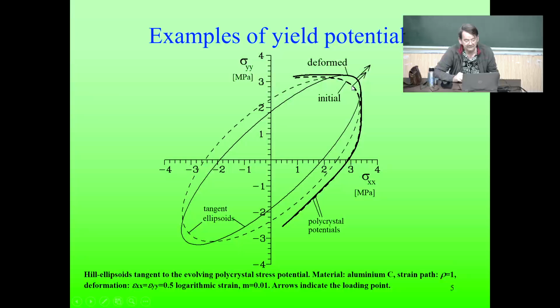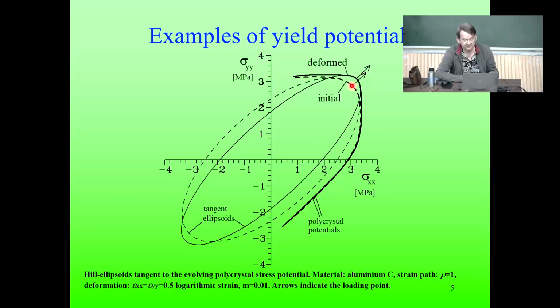Okay, and then we deform the material in equibiaxial stretching. So this is our loading point. It is going to move into this point here. Oh, I lost my pointer. Okay, so this is the loading point, which is moving into that point after a strain of 0.5 logarithmic strain. Strain rate sensitivity is 0.01, small, but still we have to do the correction for the yield potential to make it very precise. So this is aluminium material, and this is a kind of concrete example.